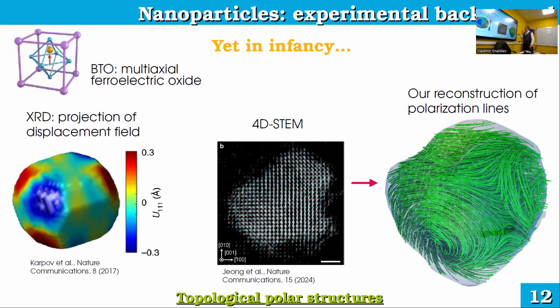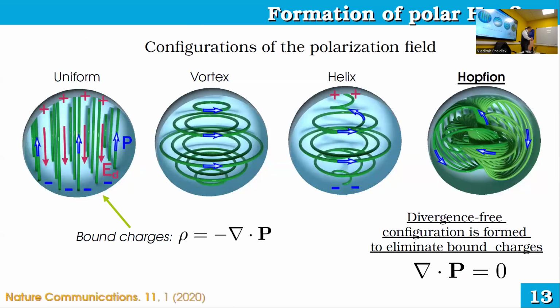But thanks to open data, we reconstructed the behavior of polarization lines in this nanoparticle, and we acquired much more complex things than just a vortex. It was one of our main results, the Hopfion state. So first of all, let's see how we can achieve such a state, this Hopfion state. Let's start with some spherical ferroelectric nanoparticle and consider it has uniform polarization. As I already told you, it's a bad state because polarization lines abrupt on the surface, they create bound charges, and this state is not energetically favorable.